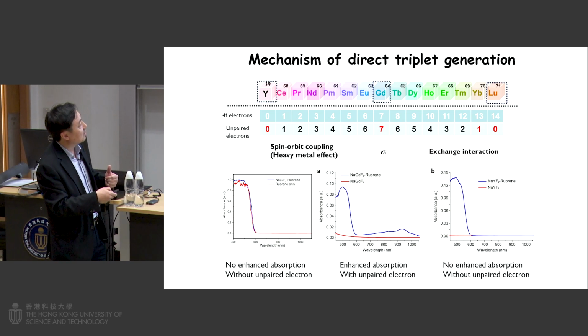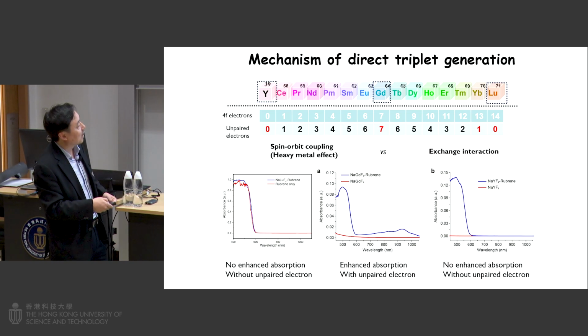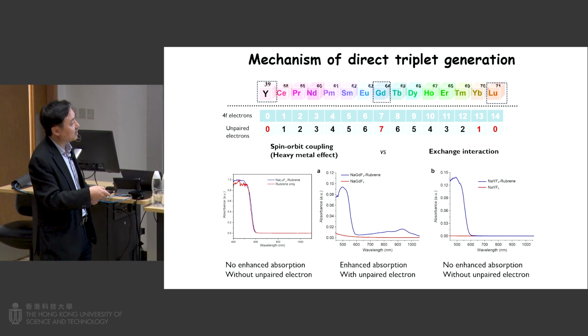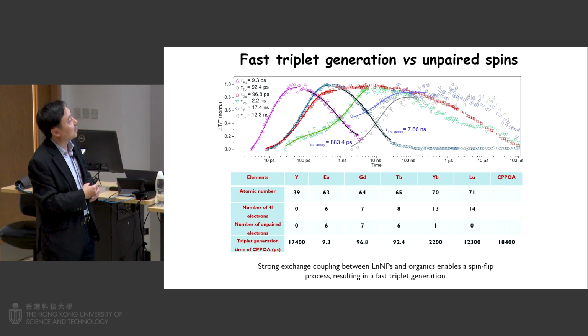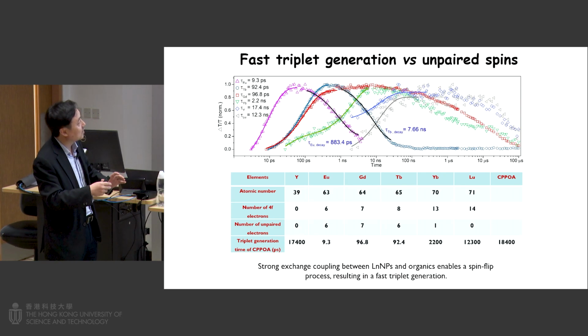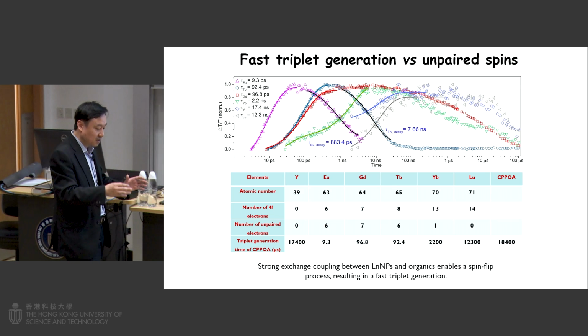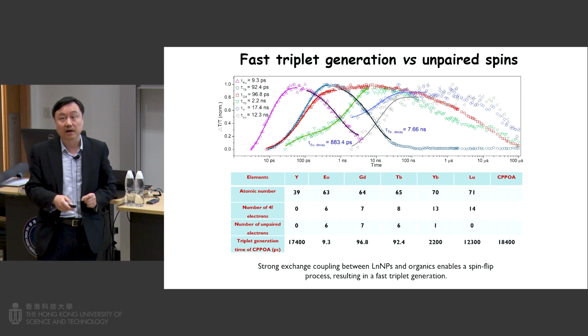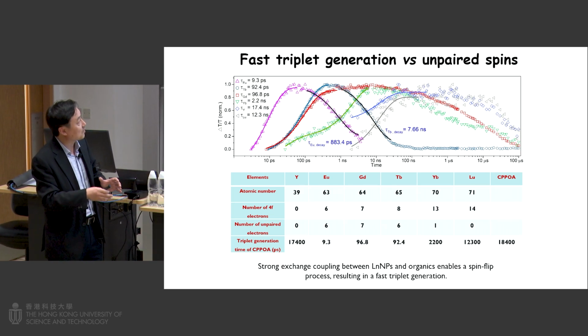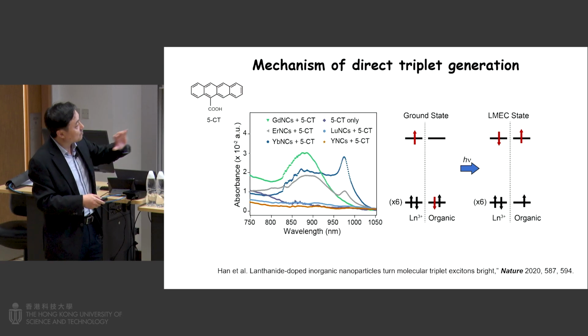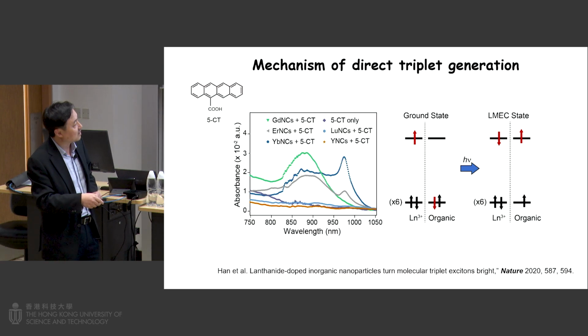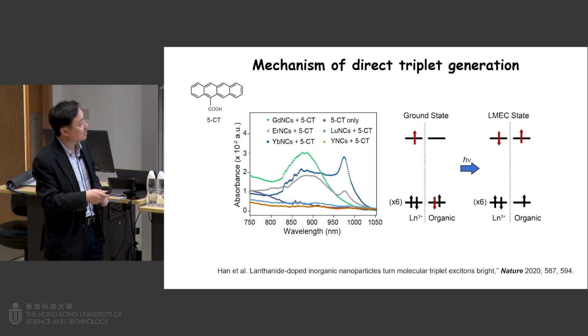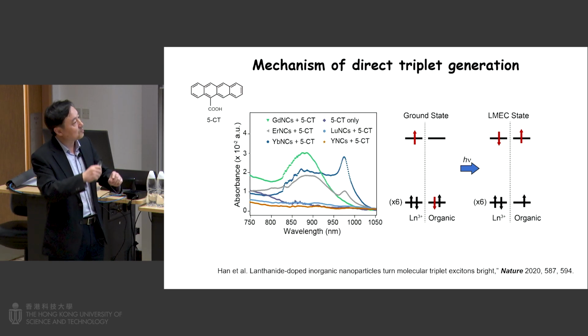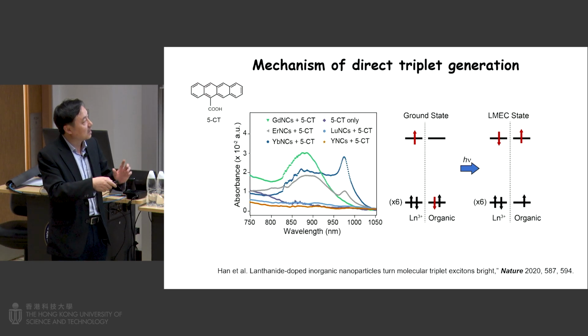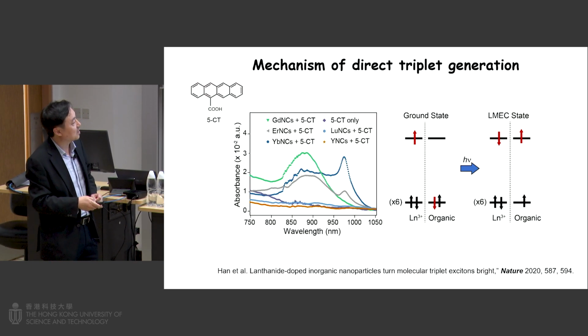So with this, you look at the results. Using Gd as the host material, we can significantly enhance the absorption. This is triplet absorption around 900 nanometers. We also did ultrafast measurements. It turns out this energy transfer between the triplet states and the nanoparticles is on the picosecond time scale. It's a very fast process. We believe the energy transfer mechanism between the lanthanide and organic is a spin exchange process. Once the organic promotes this triplet state, it also tends to spin flip the lanthanide ions, spin up to spin down here, to achieve this direct triplet generation.